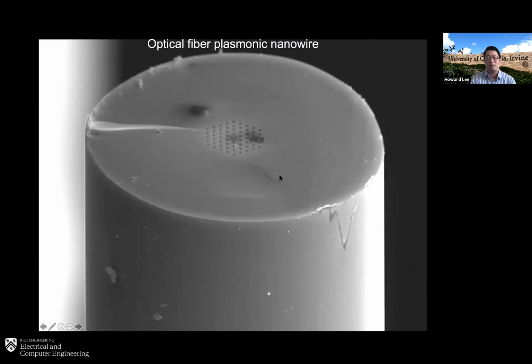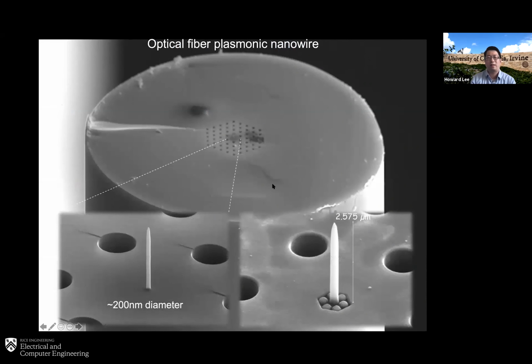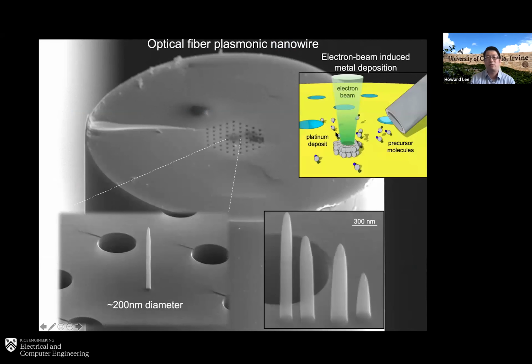So I think my time is almost up. Maybe one last thing is, instead of making metasurfaces, we're also growing nanowires. For example, using electron beam induced metal deposition, we're able to grow a nanowire at the end face of the fiber. And we can really precisely control, for example, length and width by using this technique here.